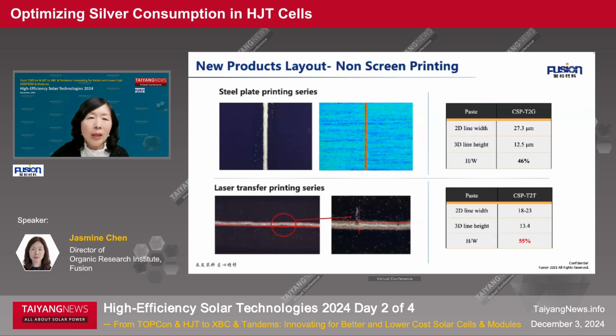Now I will quickly introduce our next generation of new product layouts. The first one is non-screen printing. We use the steel plate and laser transfer printing, which gets a very narrow line width, within 28. For PTP, laser transfer printing, it is only 18 to 23, and the efficiency is at least 0.1 higher than regular screen printing.